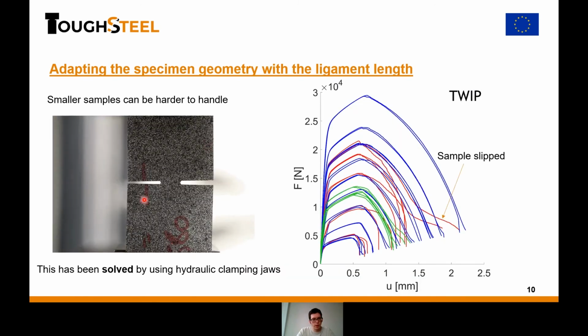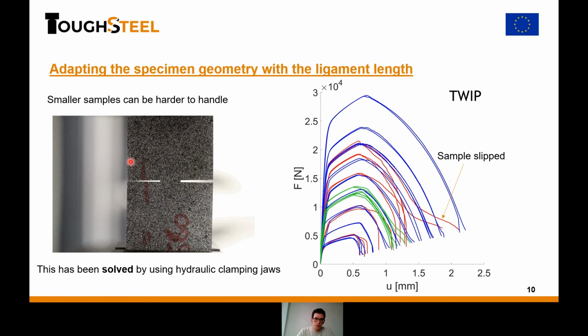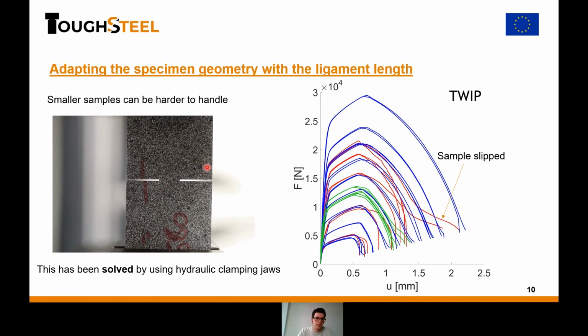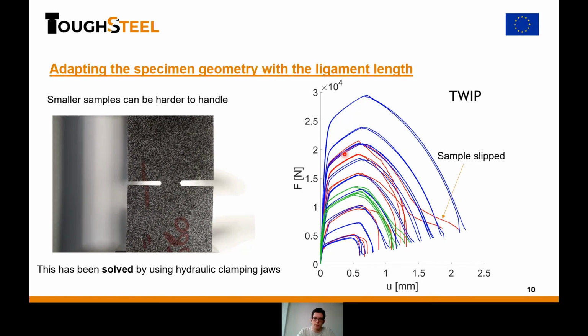And so here, this is what I was talking about: smaller samples can be harder to handle. So we had a problem. This was my first series of tests. We were not as prepared as we are now to make this test, but you see that with the clamping rod that we used and with this material, the sample was rotating and slipping inside the jaws, and so you had a shift inside the material, which means that this is not valid. You see on the force displacement curve, the blue one again is for the identical sizes and the red one for the adapted sizes.